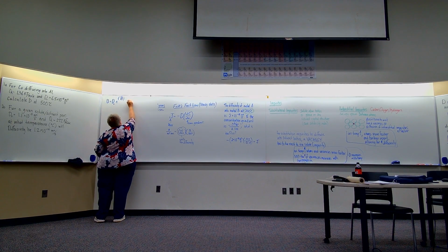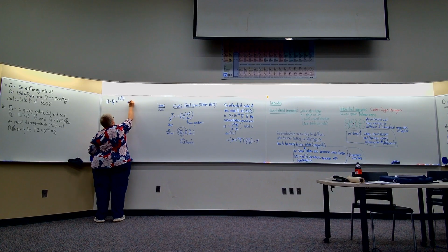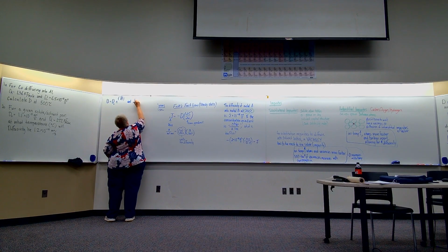And while we're here, let's also note that we could also use the equation natural log of D is equal to natural log of D0 minus Q over RT.